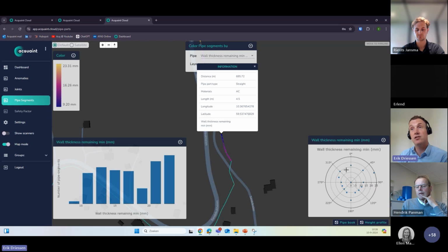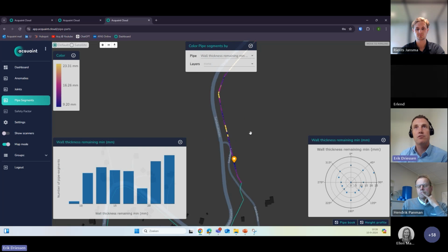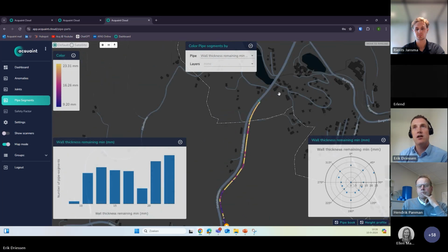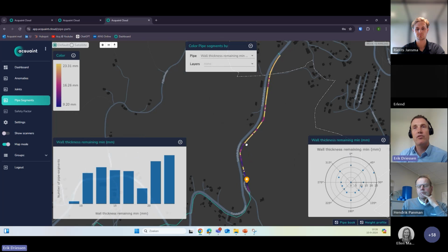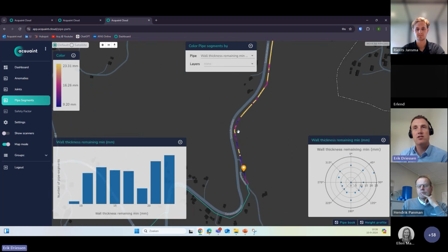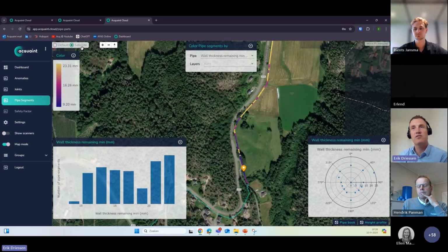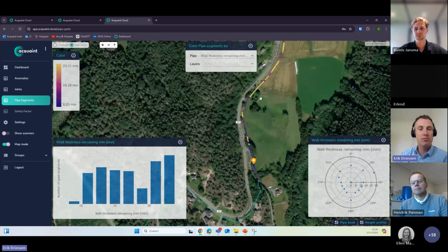So for this pipeline, the minimum wall thickness on basically all the clock positions is heavily degraded. You can do that for all the pipe segments that you're seeing here, but this view also tells you that up till here, the minimum wall thickness is fairly stable, but here suddenly there's something changing. Sometimes it can help to enable the satellite view to see what might be a cause coming from the ground level. What we see in the Netherlands often, for example, are agricultural activities like fertilizers or those types of activities, which could cause damage to the AC pipeline.